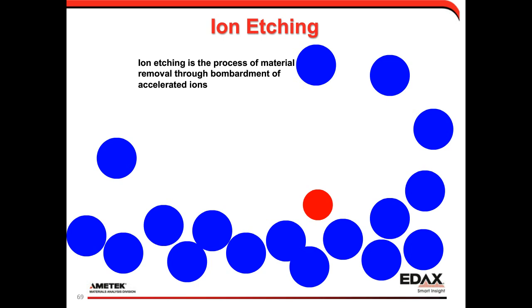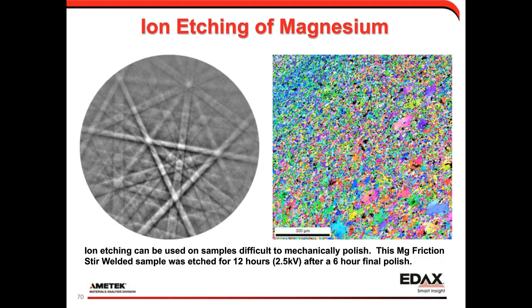And so this is just an example of a magnesium sample. This is a magnesium friction stir weld that we etched with a broad beam source at low voltage, 2.5 kV, to get the patterns.